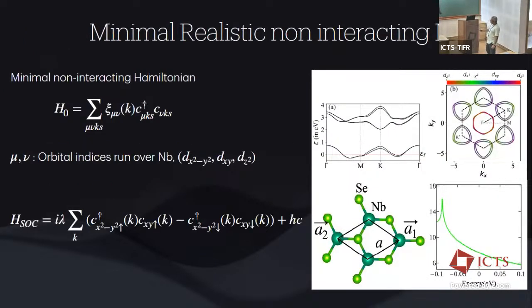Now, the model that we chose for this particular system is a tight binding model, a low energy model, which pretty accurately reproduces the density functional theory derived band structure at low energies, at least for these gaps. This material is lucky to have a relatively large splitting between these high energy conduction bands and the bands which cross the Fermi level. You need to consider minimally 3 orbitals sitting on a metal site: the x² − y², xy, and z². And additionally, you have to include Ising type spin orbit coupling in the system, which primarily couples the x² − y² and xy orbitals. From first principle calculations, the form would be more complex than this, but you can actually see the structure.